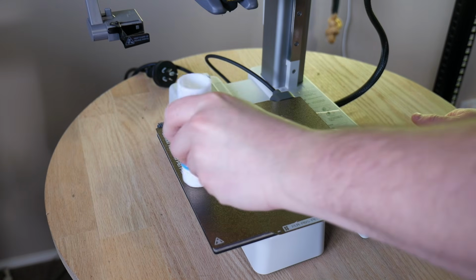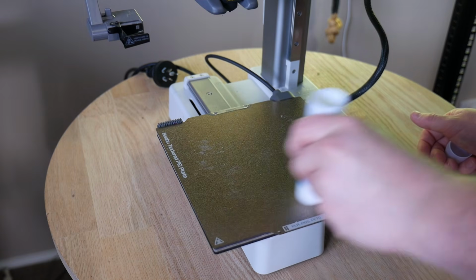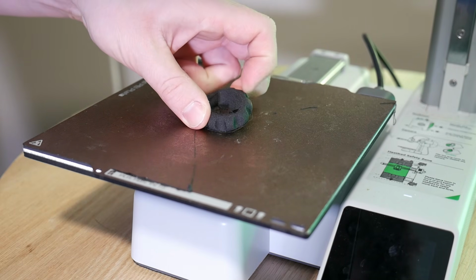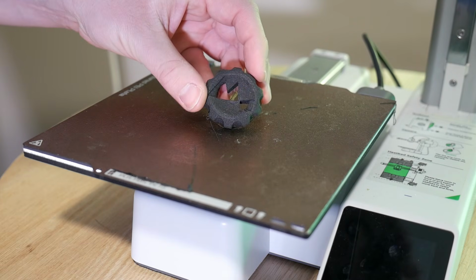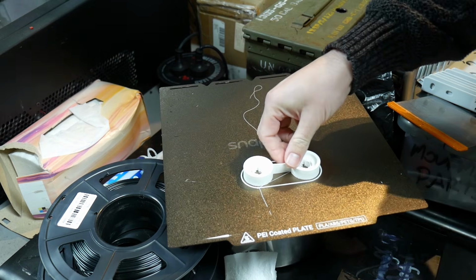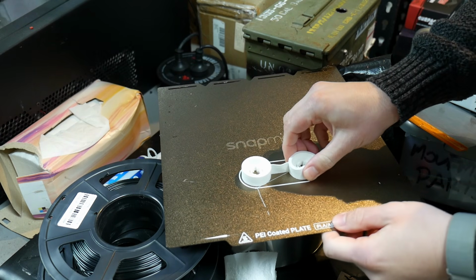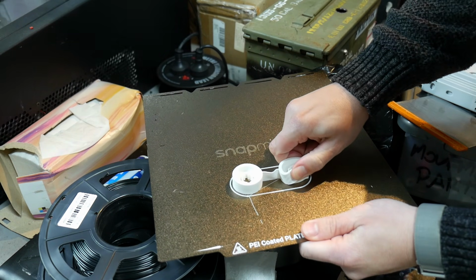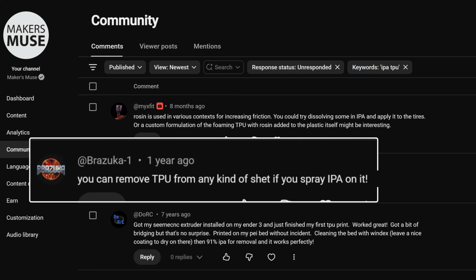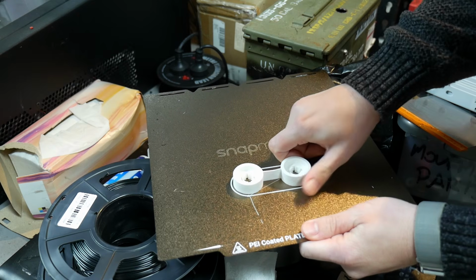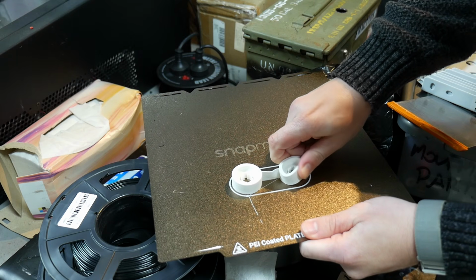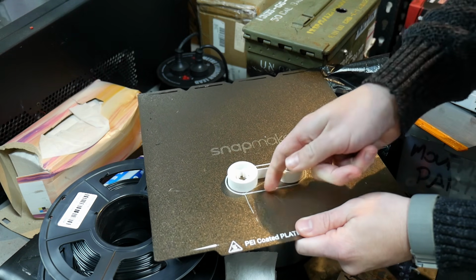This is why I've always advocated for putting a thin layer of glue stick onto the print bed when you're printing with TPU, because it actually acts as a release agent to help the print come free afterwards, and it's a habit that's been reinforced by those horrible moments of ruined print surfaces. However, sometimes I'm lazy and I forget, and I end up with prints like this, hopelessly stuck to the print bed. And that's when I remembered the internet tells me that I can release these TPU prints with isopropyl alcohol. Apparently, you can spray isopropyl alcohol or methylated spirits onto the base of a stuck TPU print, and it will magically release. This only came across my radar recently, and I have my doubts, so let's find out.